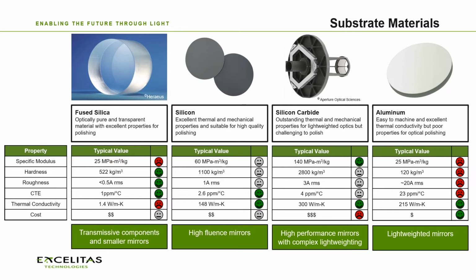Fused silica is the most optically pure of the materials. It's typically used for transmissive optics and for reflective optics where the thermal expansion coefficient is really a key consideration. Fused silica lends itself very well to very high quality polishing. So for the most critical optical requirements, where surface quality, surface roughness, and scatter are the most important aspects, fused silica is a common choice.